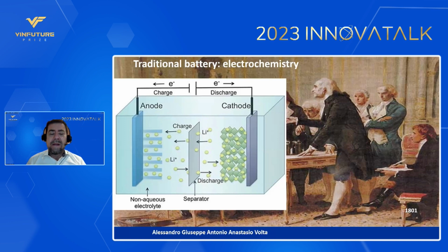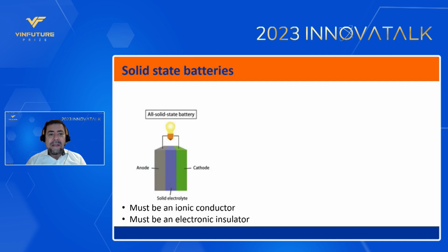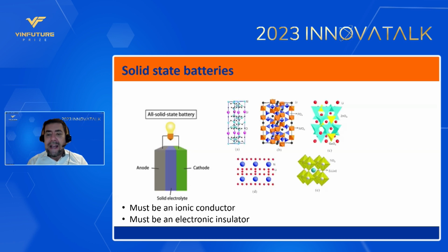So then people started to think whether we can replace the liquid electrolyte by a solid electrolyte. So a solid-state battery works more or less on the same principles as the liquid one. You have a cathode and an anode, and then the solid electrolyte is a material that can transport ions, but it cannot transport electrons, right? So it has to be an electronic insulator and an ionic conductor. So you might ask, are there many materials that have these properties? And indeed, there are several that have been studied over the years. And usually the way people deal with this is trial and error. So they make different crystals of different materials, and then they test whether this material can conduct ions or not.